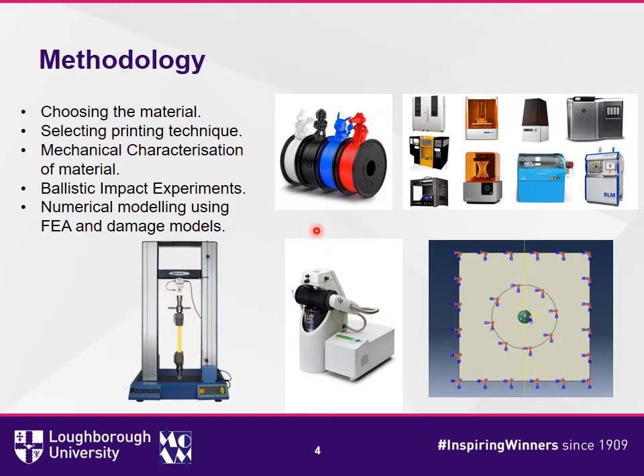The first step of the research was to select the material to investigate and the method to fabricate the structure. This was followed by a series of mechanical tests to characterize the material and get its properties for such a fabrication technique. Then a series of ballistic impact tests was carried out to understand its fracture behavior under dynamic load. And finally, numerical modeling using finite element analysis was carried out with a preset damage model and compared with experimental results.